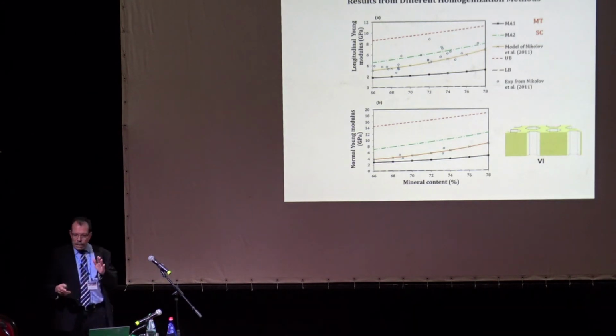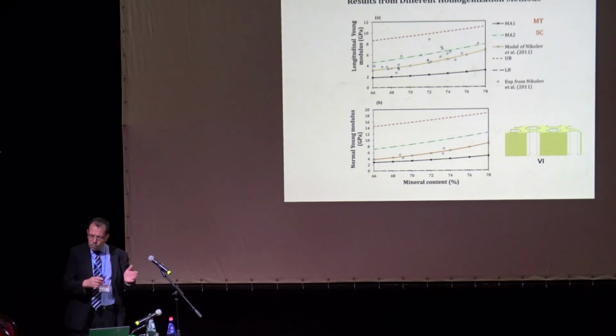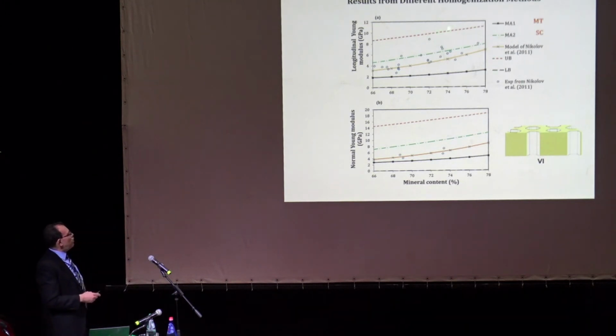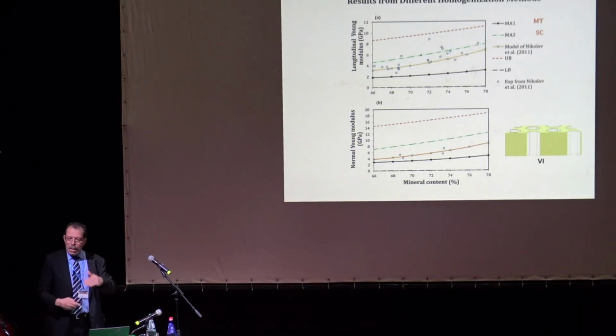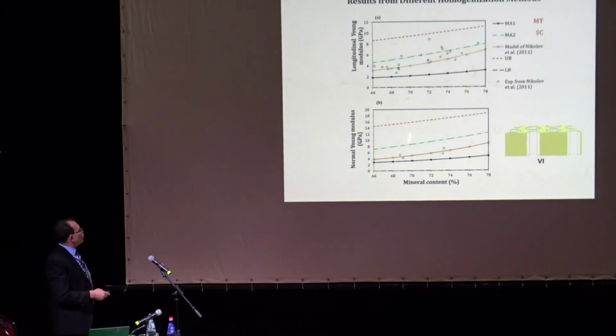So we should not be surprised that some models might not work at all, some might work a little bit because of these things. If we compare now, we use the upper bound, this is what you get. This is lower bound. This is for longitudinal, and this is for normal, I call it transverse, Young modulus. And for longitudinal, this is the upper bound, this is the lower bound, okay? Very simple averaging. And these are the experiments by Nikolov, okay? And this is the initial work by Nikolov, okay? And here you have the Mori-Tanaka based, which gives us very close to lower bound, okay? And self-consistent, as you can see in green, overestimates. So Mori-Tanaka at different levels underestimates, and self-consistent overestimates. Same thing for the normal Young modulus.